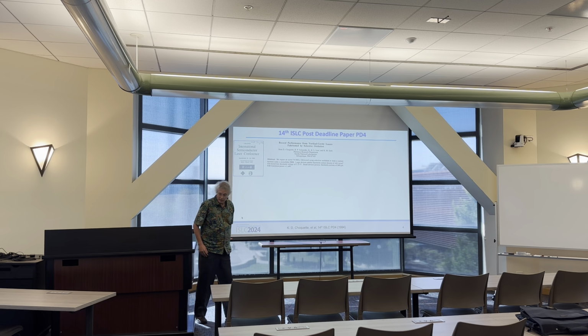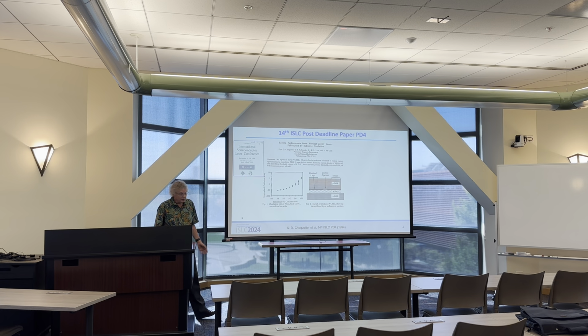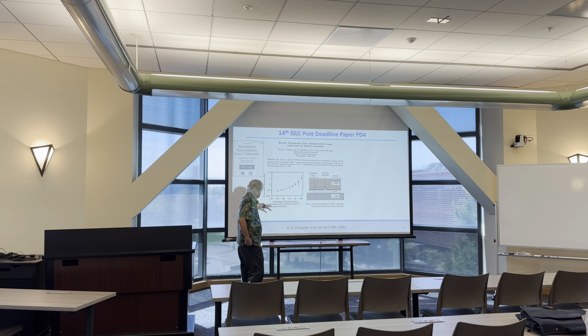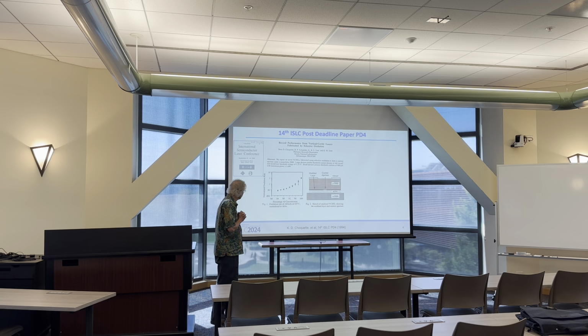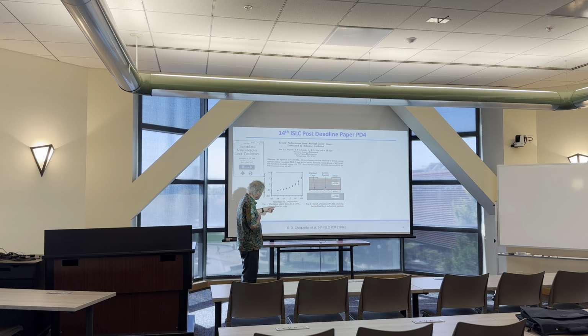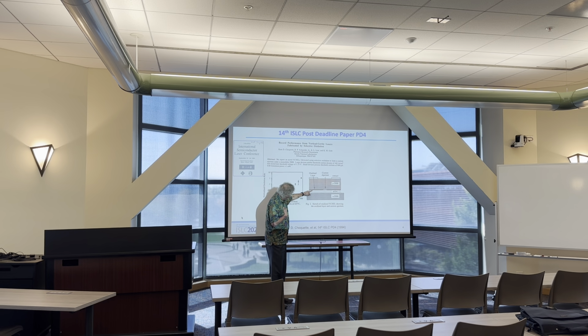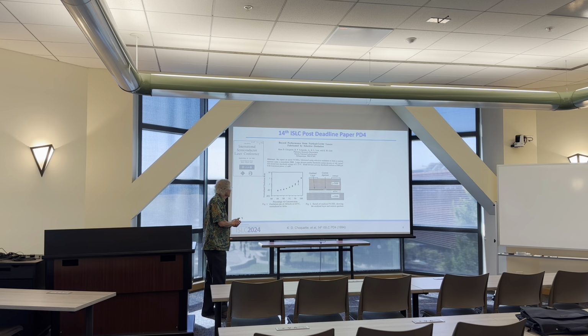So this was the paper that we presented. In it, we showed work looking at the oxidation rate relative to aluminum arsenide, and found that you could vary the rate very carefully with selective control of the composition. So you could put an oxide aperture buried inside a monolithic DBR, which was then and now the structure for VCSELs. And it works really, really well.